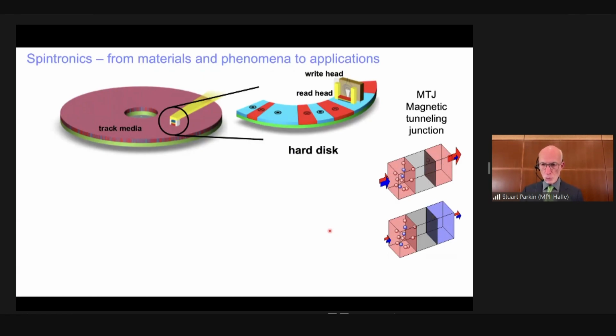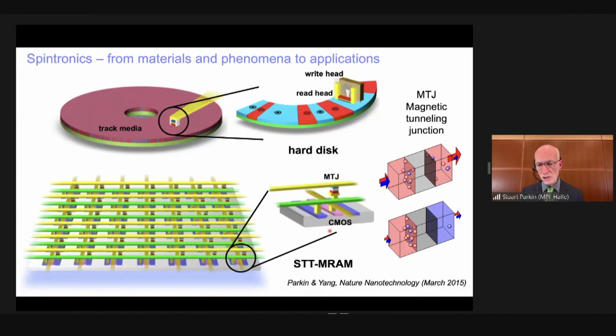However, at the same time, one could use the same magnetic tunneling junction as a memory element. Here you store information in the direction of the magnetic moment of one of the magnetic electrodes. So shown here, the right magnetic film is magnetized to the right or to the left, red and blue. And we design a device so that the magnetic orientation of these layers will be retained for up to 10 years at room temperature and above, in fact, up to temperatures as high as 150 degrees centigrade. So this can be a memory device. And because of the very large change in tunneling resistance, one could read the state of this memory device very, very quickly. This is something that we actually proposed in 1995.